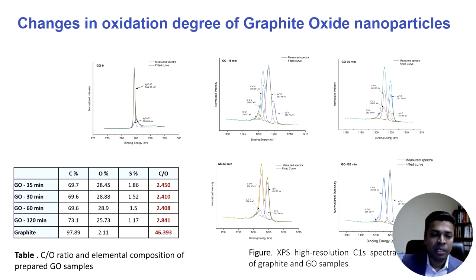So the basic idea of this research is to use graphite oxide, change the oxygen functional groups in the graphite by adding oxygen functional groups by oxidation, and then use those differently prepared graphite oxide, with different carbon to oxygen ratios and different oxygen functional groups, in the canola protein based films, and then look at the mechanical strength and the barrier properties.